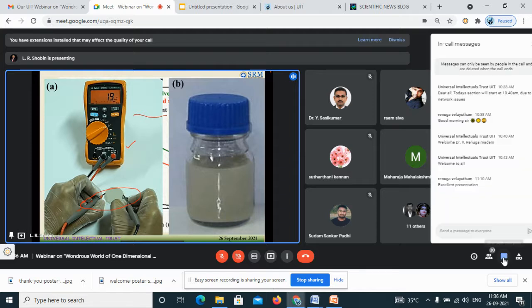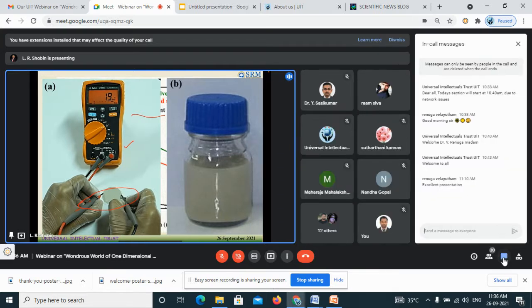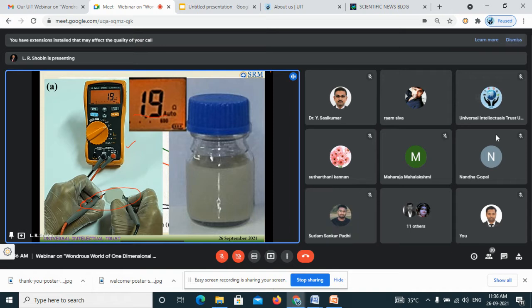films. And you are able to get a dispersion out of it also. You can create a dispersion out of it. You take a piece of this film and you can mix it with water. It will disperse actually. That is one of the major advantages of this process. So as I already mentioned, the resistance is very low, so it's metallic in nature.